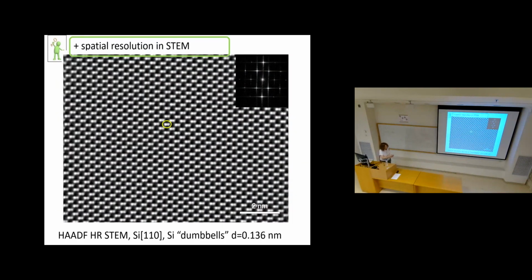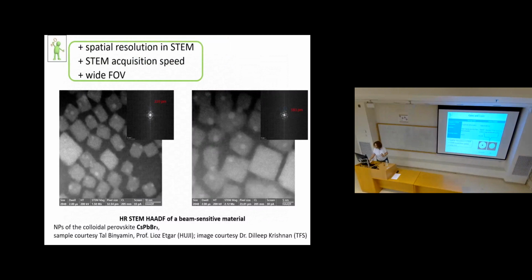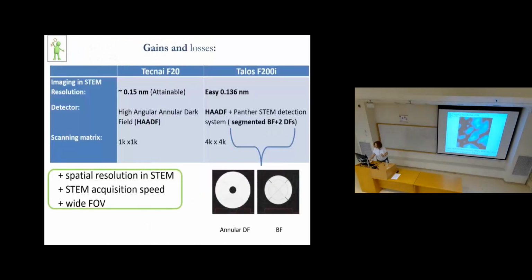Okay. So the dumbbells labeled here in the yellow ellipse are the atomic columns of silicon atoms in the lattice of silicon oriented with the 110 parallel to the beam direction, and the separation between these two columns is 1.36 angstrom, and it is clearly visible. It is even relatively easy. And more, I will skip for a while. Let me show you something else.